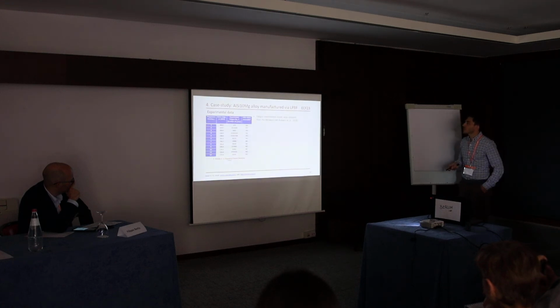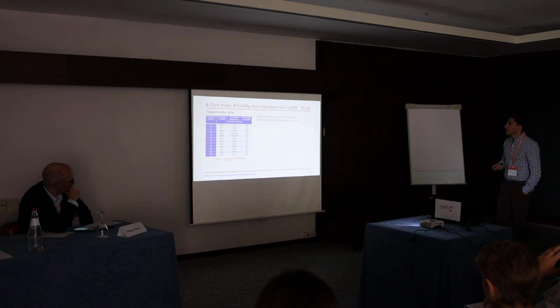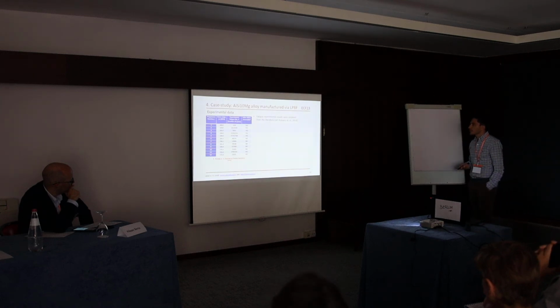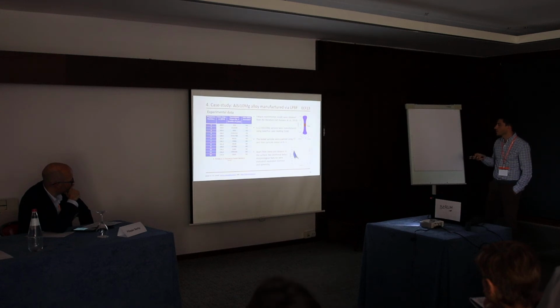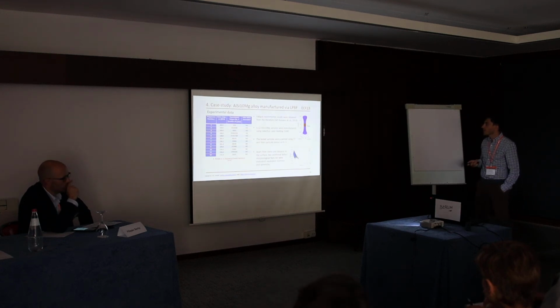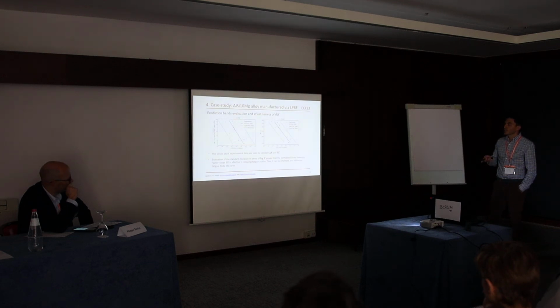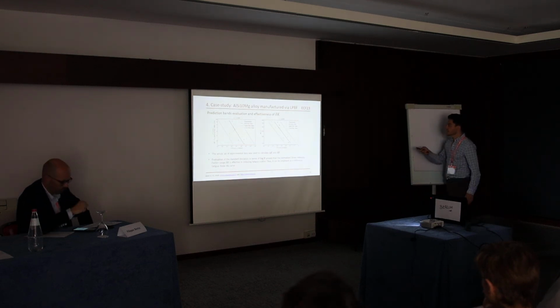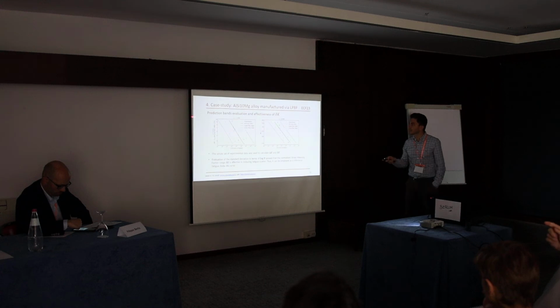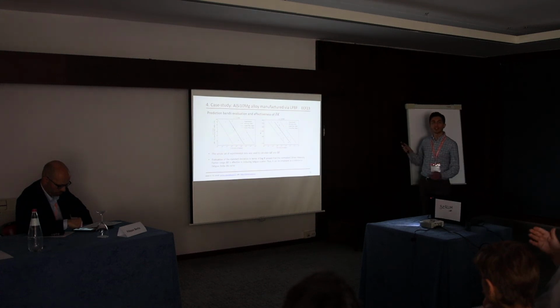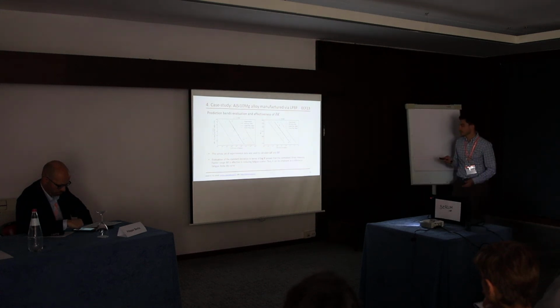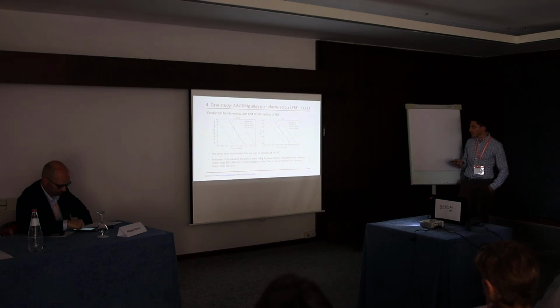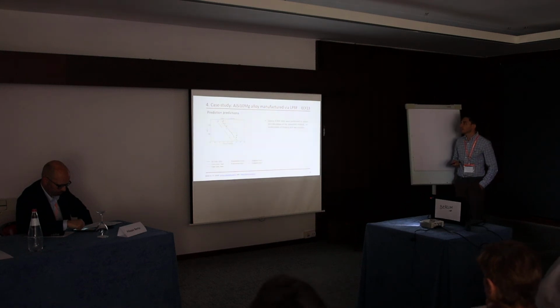The validation is done through an experimental data set provided by Romano and Beretta. They provided us 12 samples. They've done CT scans, they loaded them under fatigue at R = -1, and they also provided the sphericity and the equivalent diameter. So first of all, we evaluated whether the normalized stress intensity factor was effective, and we realized that it was actually effective. It gives a narrower scatter band, so it can be employed. And then we did the actual prediction.